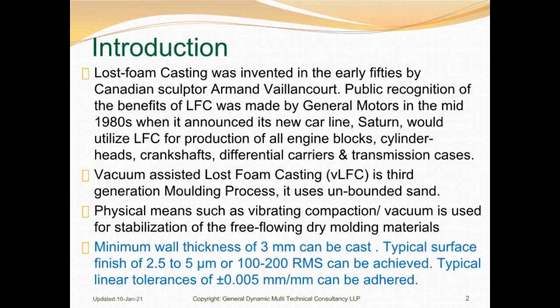Vacuum Assisted Lost Foam Casting, VLFC, is a third generation molding process, and it uses unbonded sand. Vibrating compaction and vacuum are used for stabilization of the free-flowing dry molding materials. Minimum wall thickness of 3 mm can be cast. Typical surface finish of 2.5 to 5 micron or 100 to 200 RMS can be achieved. Typical linear tolerances of plus or minus 0.005 mm per millimeter can be adhered to.